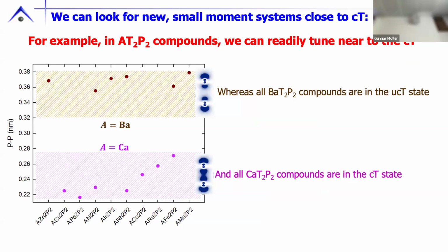And by the way, for those of you who like looking at crystallographic tables, you have to be super careful here. You have to make sure this is based on X-ray data where the whole unit cell, the whole basis, was determined. Sometimes they will assign parameters based on unit cell dimensions, but they haven't determined the basis. The problem here is the phosphorus or the arsenic has a non-symmetry-defined dimension. So you have to make sure of the purity of your data if you make a plot like this. The ones that are missing data have been measured for unit cell size, but they haven't figured out the basis. A comment for experts, perhaps.